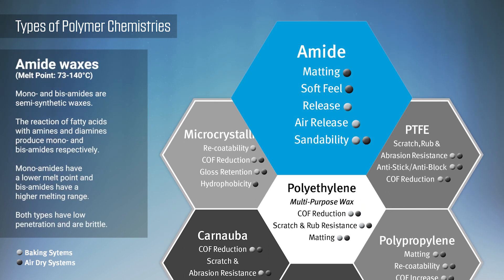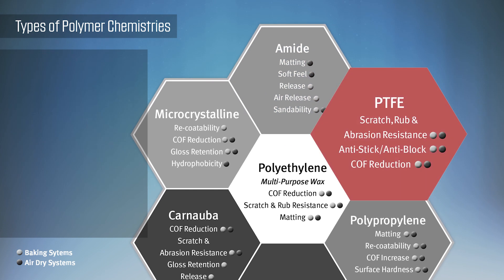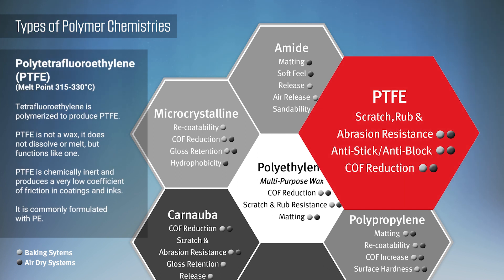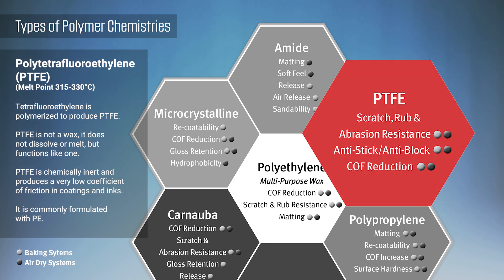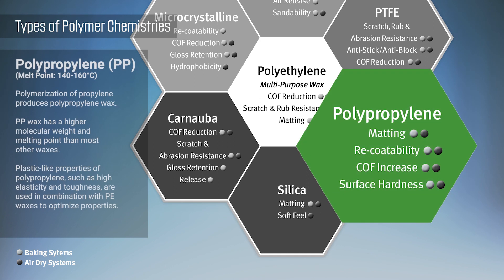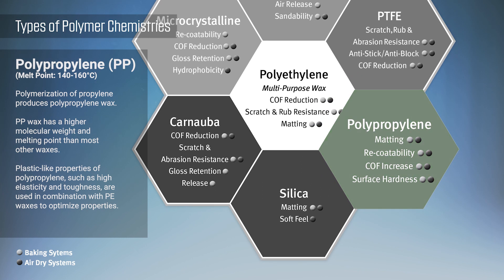Amide waxes provide release and anti-blocking properties to surfaces or soft coatings that come in contact with sticky foods. PTFE provides the highest level of mobility and scratch resistance and can create surface effects like texturing in powder coatings. Polypropylene waxes are hard polymers with very good scratch and abrasion resistance that can also reduce gloss in the finished film.